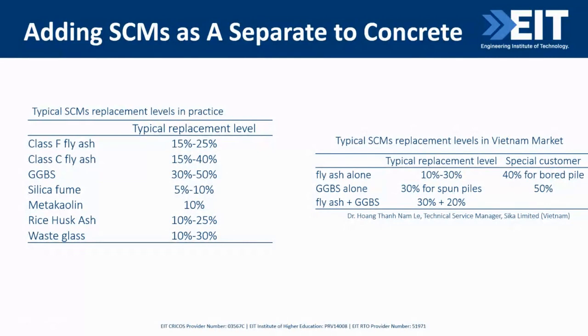Then glass powder. Glass powder can be used to replace Portland cement, typically at 10 to 30% replacement level by weight. While concrete is in its plastic phase, glass powder will increase its workability, so it actually requires less energy, cost, and time to place and to consolidate the concrete. But while the concrete is in its hardened phase, concrete containing glass powder actually exhibits better strength, freeze-thaw resistance, and sulfate resistance.